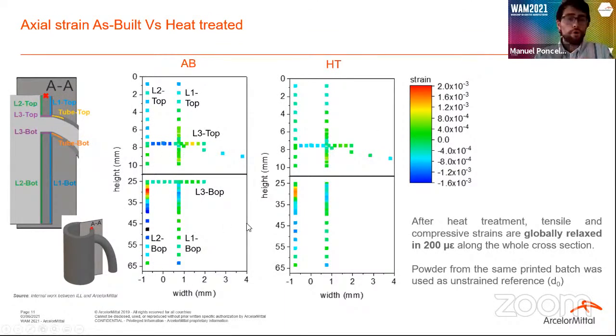So it can be seen that globally there was a strain relaxation after the heat treatment, which is what we were looking for. And also what is very interesting for us is the sharp gradients that you can find in the Z direction. For example, if we look at this L2 line, which is representative of the inner cylinder surface, there are very sharp gradients over a small distance, but also there are gradients between the inner and outer surface, so in the XY plane. That's something that we were not really expecting.